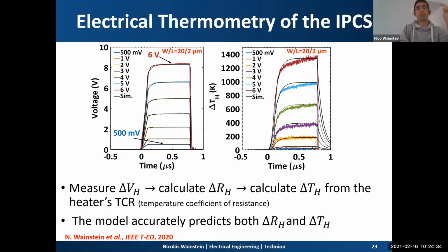Furthermore, we presented for the first time electrical thermometry of operating IPCS devices. These measurements were used to calibrate the model, and as you can see here, as temperature of the heater rises, its resistance changes according to the temperature coefficient of resistance, or TCR, of the heater material. This in turn changes the voltage drop at the heater. So by measuring the voltage variation at the heater, the resistance change can be determined, and then it can be converted to delta T using the TCR of the tungsten of the heater.